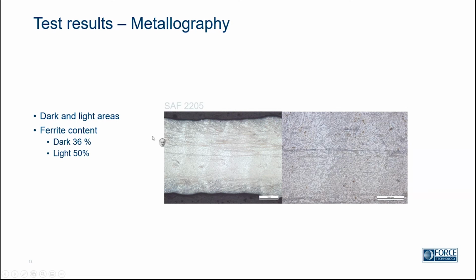And with this being a duplex steel, it's important to also control that we have the right amount of different phases in the steel. And yeah, here the ferrite content is controlled, and actually both the dark and the lighter areas are within specs for 2205. And then of course we will also look at irregularities, or whether there are intermetallic phases that might be more critical in something like aluminum, where some intermetallic phases can cause corrosion to the aluminum matrix. And in this particular case, we saw some secondary austenite, although not critical. It's just not something you would see to the same degree in conventional material.